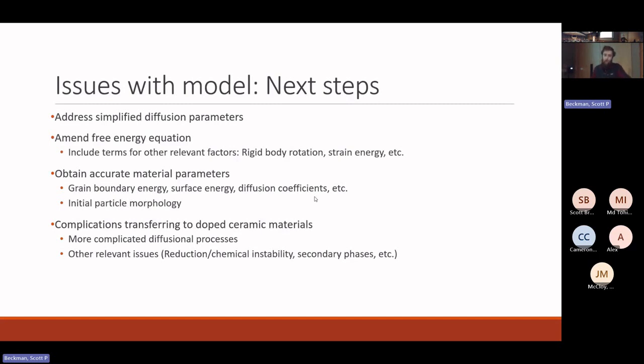Additionally, the free energy equation is missing a few relevant terms as well, including rigid body rotation and the strain energy of the system, both of which are highly relevant to sintering processes but were not included in this relatively primitive simulation.